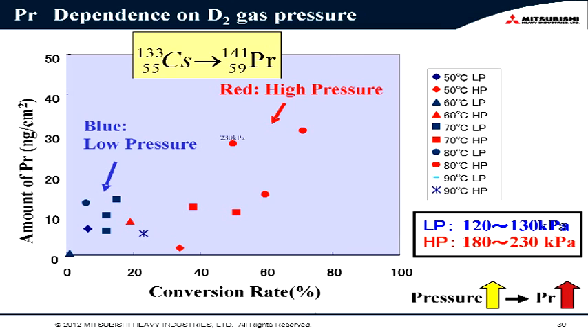This is the amount of praseodymium in nanograms and the conversion rate here. The conversion rate is half the portion of cesium transmuted into praseodymium. The blue points mean low pressure, and the red points high pressure results. Low pressure is 120 to 130 kilopascals, and high pressure is 1.8 to 2.3 atmospheres.